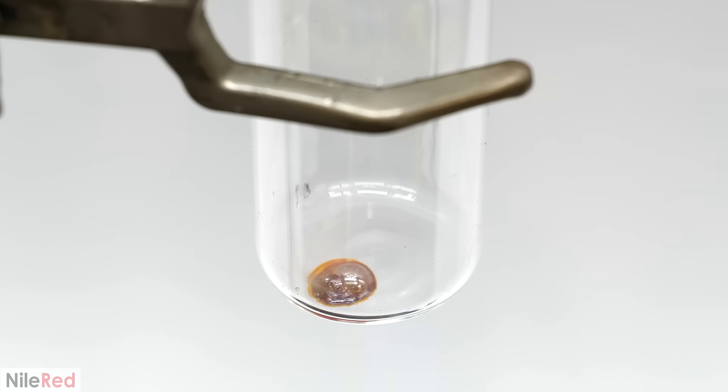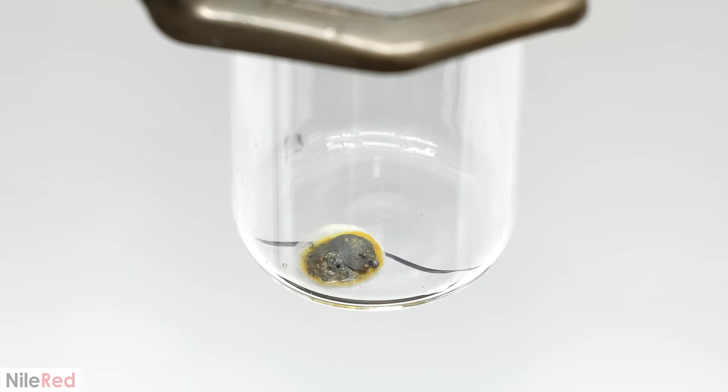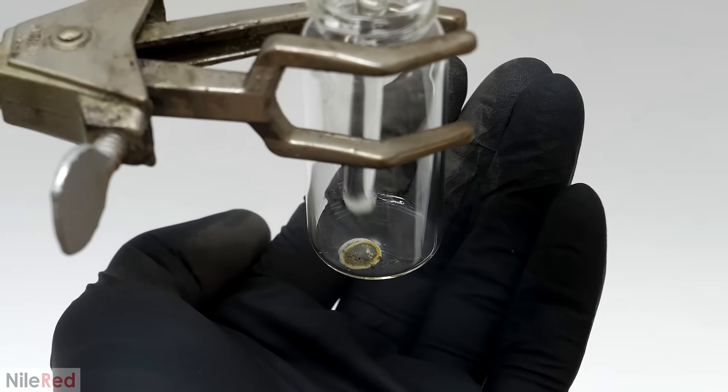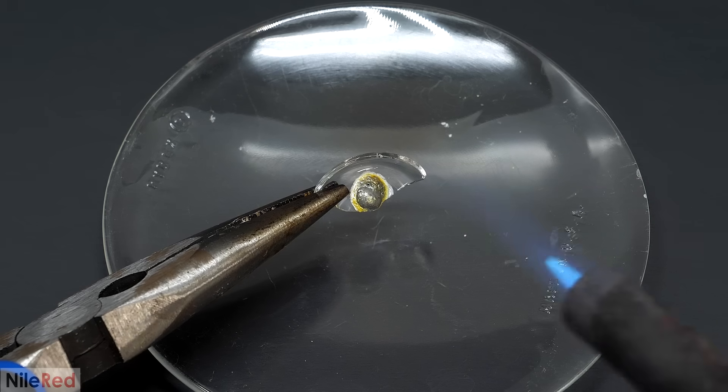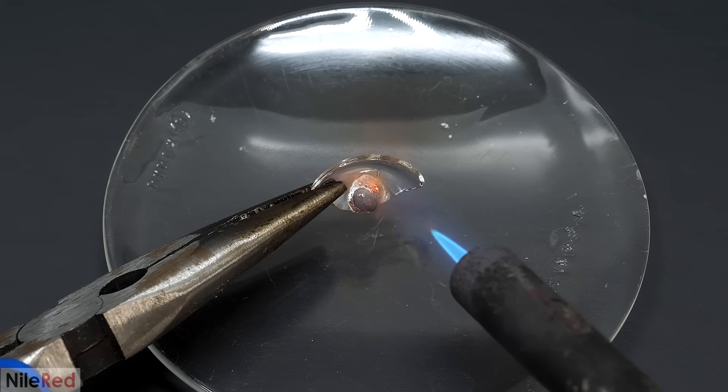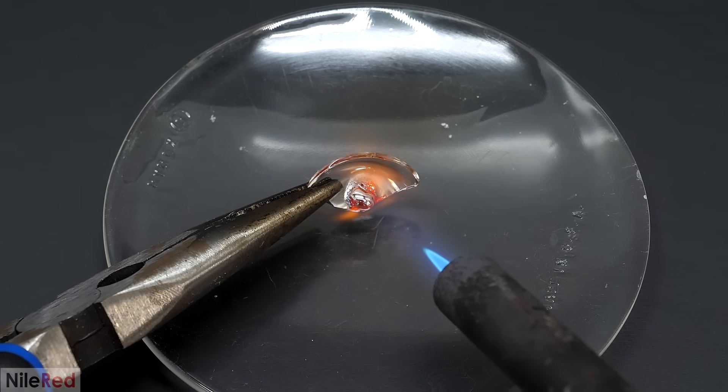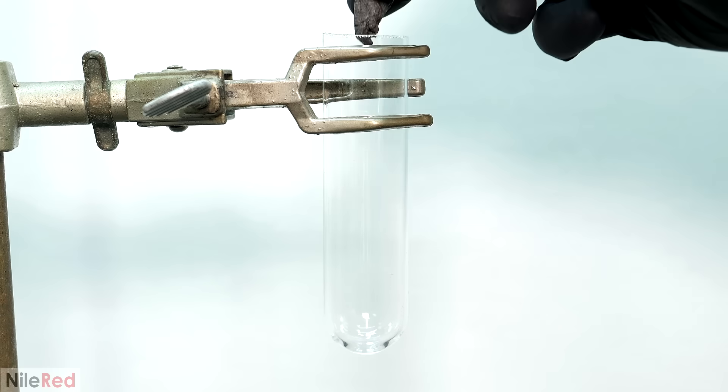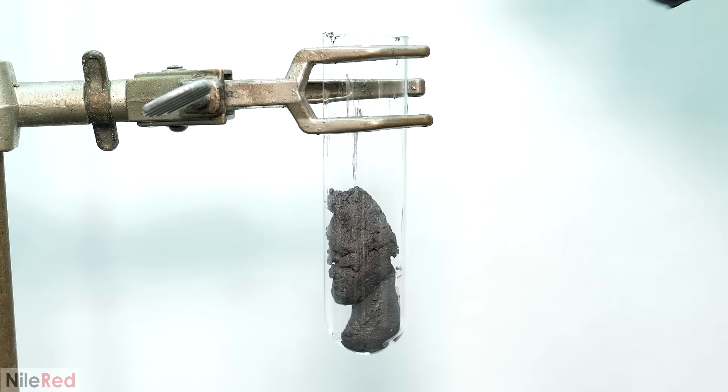This was what I found in my last video, and it was a method that I used to melt down the bismuth, but it's not exactly the best process. Not only did I find that it wasn't that efficient, it also required heating things well above the melting point of bismuth. I'm pretty sure that it gets well over 1000°C, which can cause a lot of the bismuth to start vaporizing, which is both dangerous and bad for the yield. I looked online for a potential solution to this problem, but I wasn't able to find anything decent. There was one potential one though, which suggested melting it under something like candle wax, and I did try that, but I never was able to get it to work. I instead just had to come up with something on my own, and this was what I did.